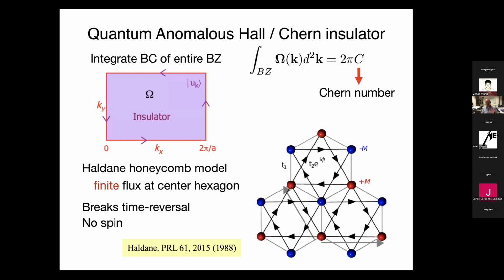And for that, these are the last 5-6 slides of my talk. It will become a little bit theoretical now. For that, we considered a honeycomb system where we have nearest neighbor hopping and also the presence of fluxes, which translate into the presence of next nearest neighbor hoppings. You will recognize the Haldane honeycomb model with finite flux for it. So we know that in the Haldane model, if you integrate the Berry curvature over the Brillouin zone, you get a Chern number. And if you get such a Chern number, it means that there is an anomalous Hall effect. If you dope the system so that it's a metal, the Hall effect will still be there, only it will not be quantized.